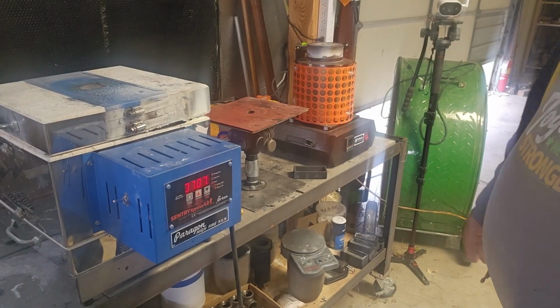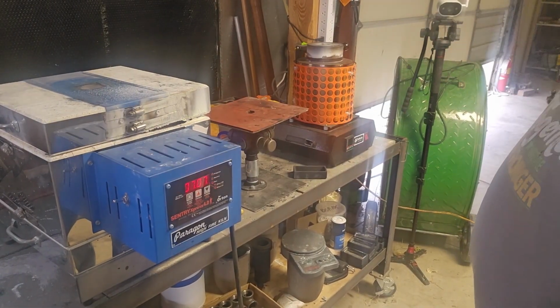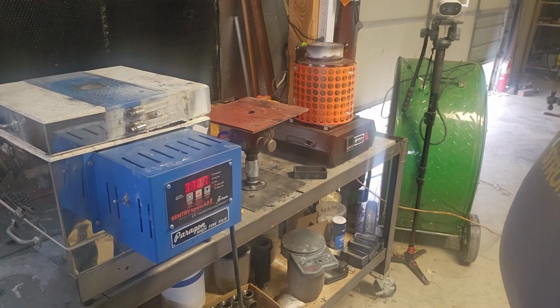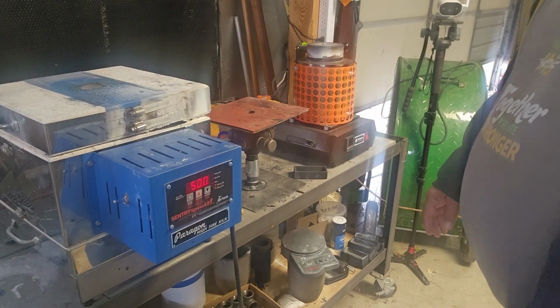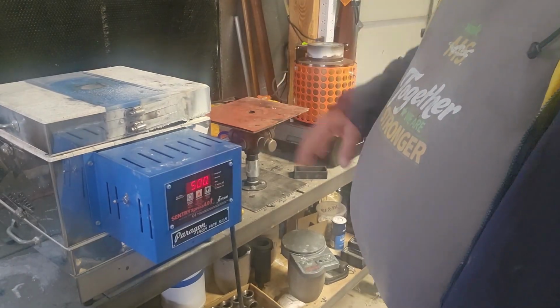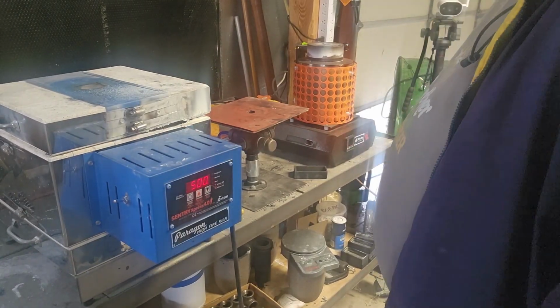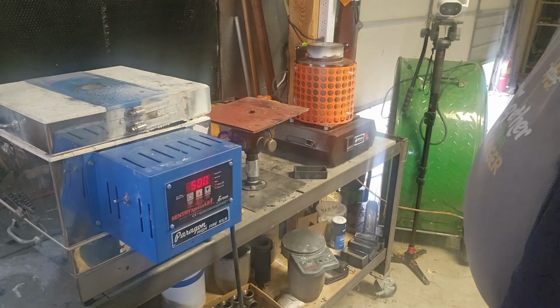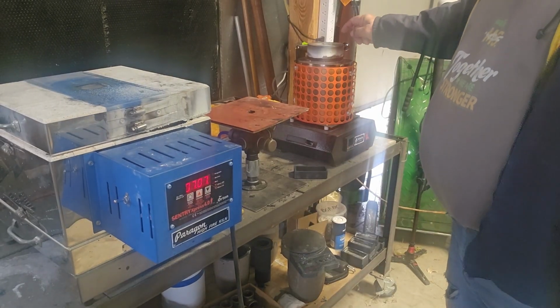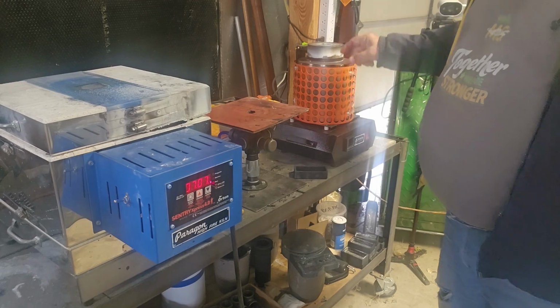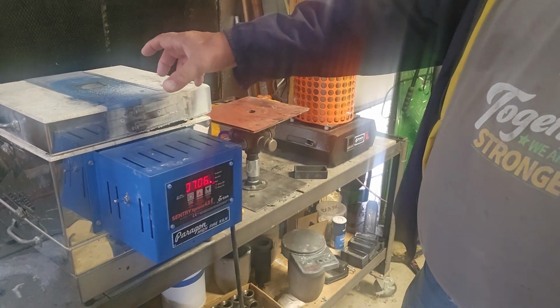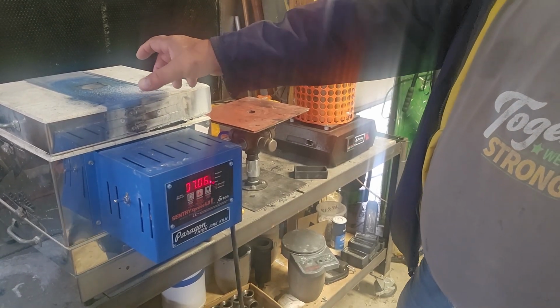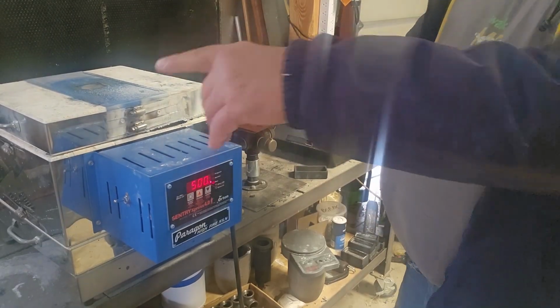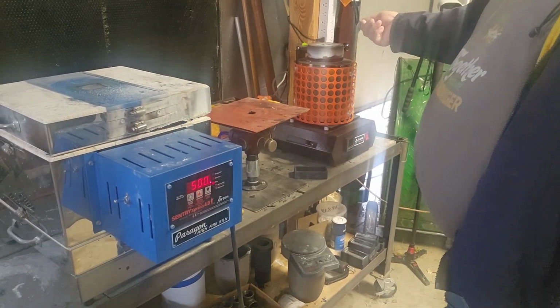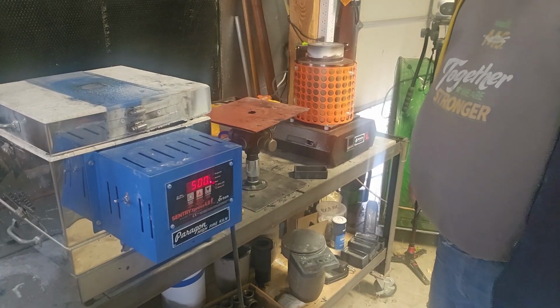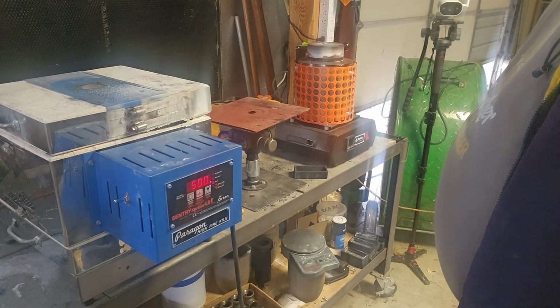Okay, here we are the next day. This has gone through its 14-hour plus process and burned out all the plastic. A lot of residue left this time. This is hot, I shouldn't touch it. So next what we're going to do is put aluminum in here, melt it, and then do the trick where we take the can out of here, set it on here, make sure we've got a vacuum seal, take the aluminum out of here and pour it into there. And so we're going to get to that.